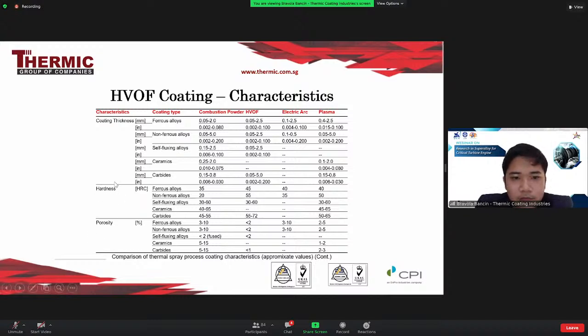For the hardness of ferrous alloys with similar or the same material, HVOF produces the highest hardness compared to electric arc, plasma, and combustion powder, because of the kinetic impact energy of the powder hitting the substrate. Because the speed is supersonic, it increases the hardness of the part, making it denser and harder. The porosity of HVOF is the lowest compared to the other processes.